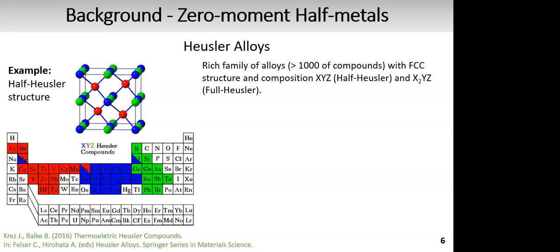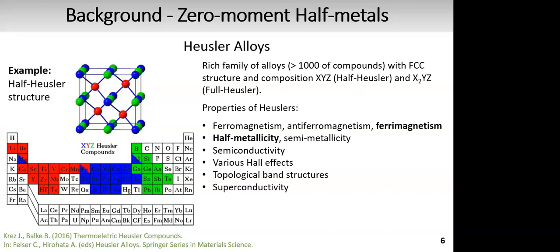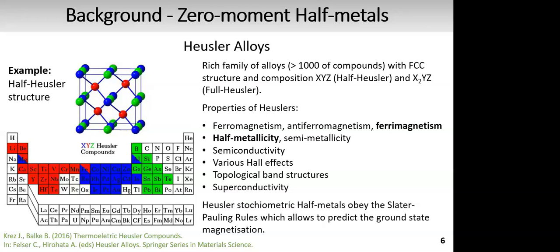So it is a rich family of over 1,000 compounds, which exhibit many properties relevant to spintronics. And this includes half-metallicity and ferrimagnetism. So this material class is a promising place to start in the search for zero-moment half-metals. And this is because the Heusler stoichiometric half-metals obey what is known as the Slater-Pauling rules. And the Slater-Pauling rules relate the number of valence electrons of the compound to the ground state magnetization, which is an integer number. So the idea is to take a Heusler half-metal and find the right composition of valence electrons in order to achieve a net ground state magnetization equal to zero.